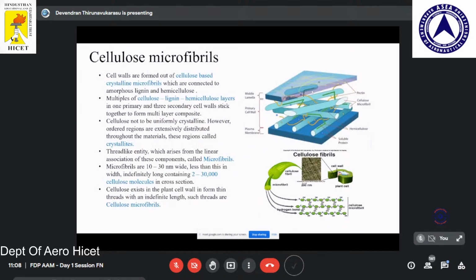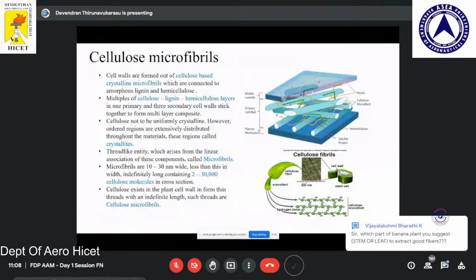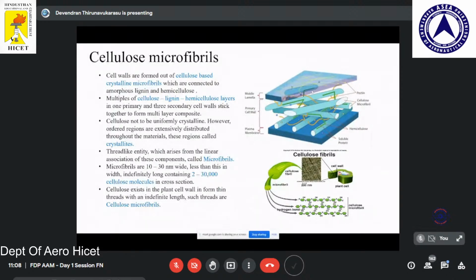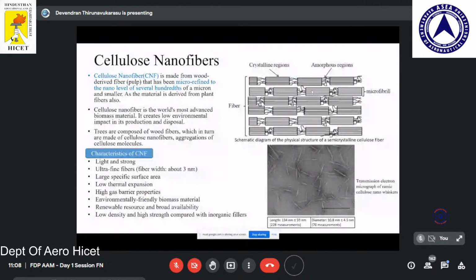These are the cellulose microfibrils. Here, in the microfibers, there are a lot of cellulose chains. The cellulose chains have a lot of functional groups, with almost 30,000 cellulose chains connected, and the size of the microfibers is 10 to 30 nanometers. And these are the cellulose nanofibers. The cellulose nanofibers have a crystalline region and an amorphous region. It's a very strong material. It's already proven worldwide. They are using it in the pharma industry and food industry, as an additive and also as a reinforcement agent. Currently we are trying to use it in structural applications for strengthening and insulation applications.